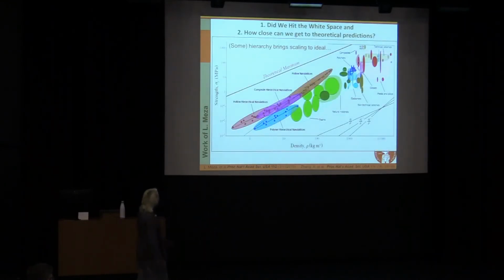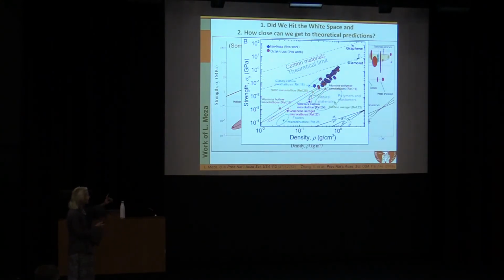All right, so now the question was, did we hit the white space? Remember, that's what we were after. So all of this is to remind you, this is the white space before, and these are all of our points, and so you can see that at least in these hierarchical fractal nanolattices, we bought ourselves 2 more orders of magnitude of reduction in relative density. This was 4 years ago. We can do much better than that, and you guys can probably do much better than that. But we certainly are showing that the combination of the nano-size effect and architecture does in fact provide a pathway to build these entirely new classes of materials.